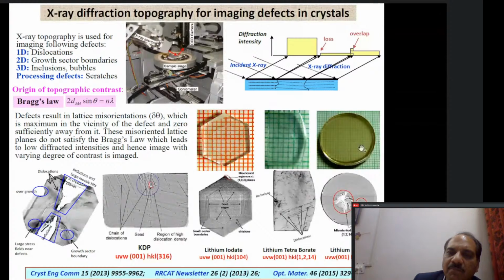You can see that the samples appear absolutely perfectly fine. They are completely transparent. But when you subject them to X-ray topography, you see the seed edges, you see striations, you see misoriented regions, you see dislocations, you see inclusions inside, which otherwise you are not able to see.